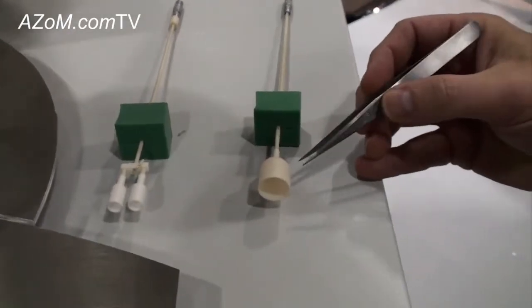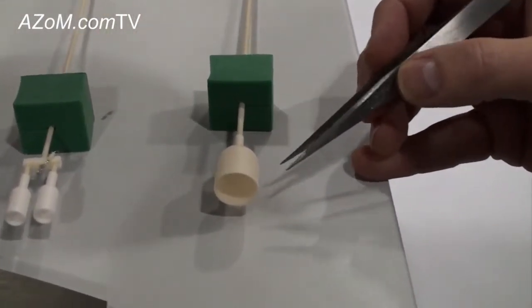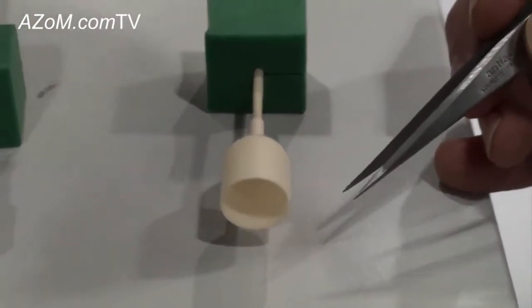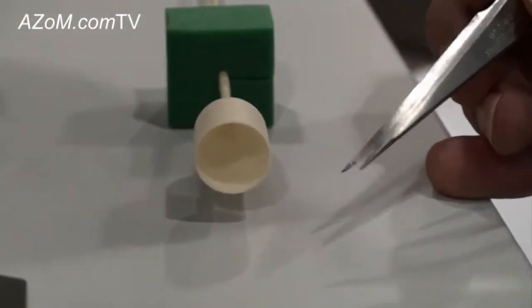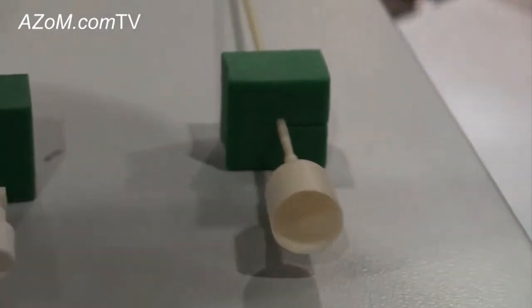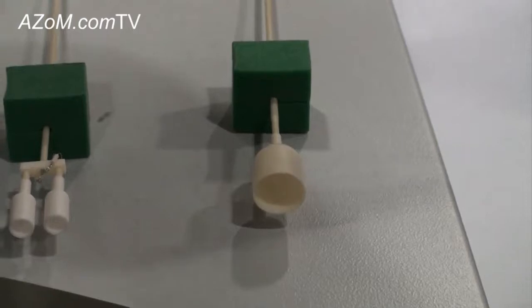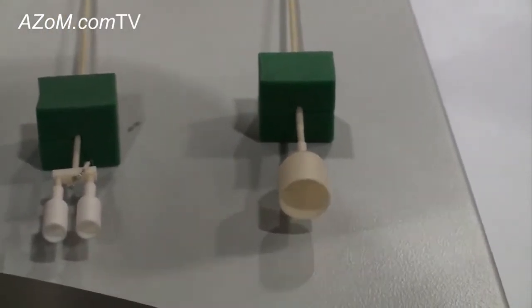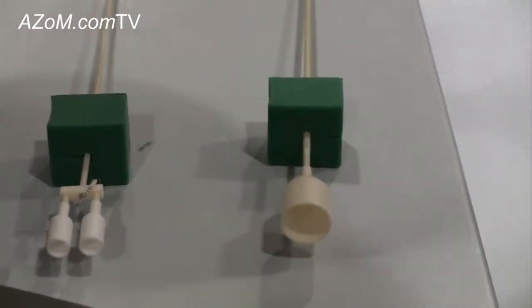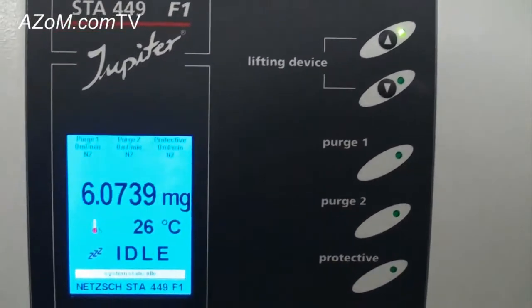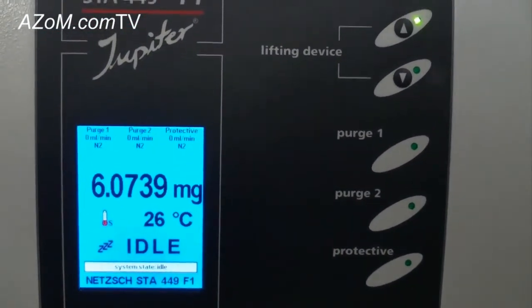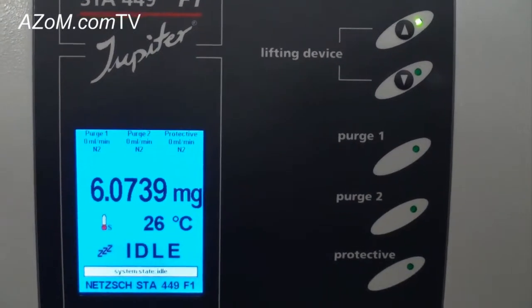Alternatively, we could use just a large volume TGA only crucible, which would allow us to make measurements on samples with volumes up to 5 milliliters. And the balance of the instrument is such that we could measure up to a 5 gram mass change, or on another instrument we could go to a 35 gram mass change. So we can measure very large masses, and we could also measure it in very small resolution. The resolution on this instrument of the balance is 0.25 micrograms, which is 250 nanograms, which is very, very sensitive balance.